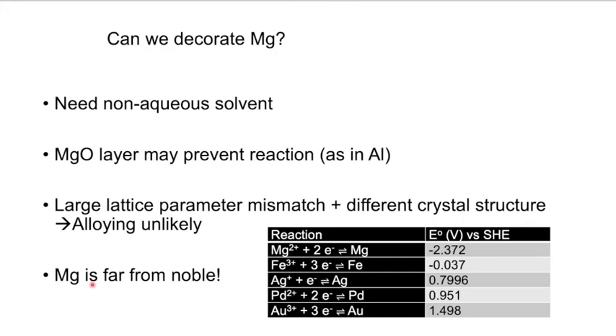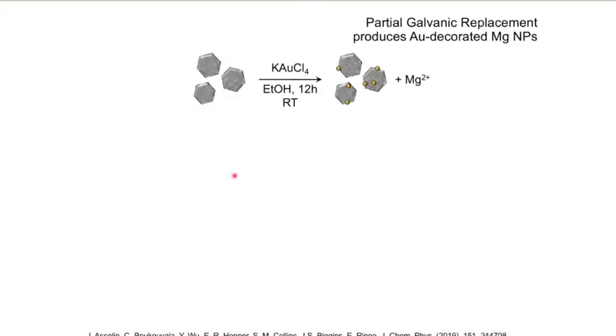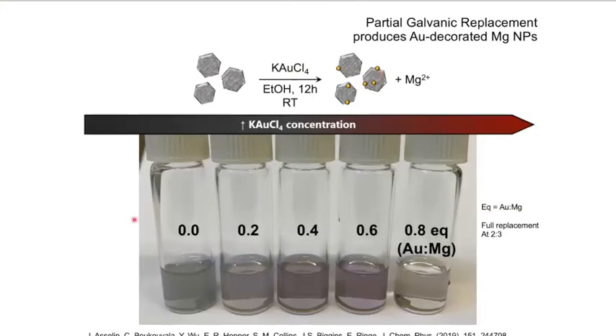And so there's a huge thermodynamic driving force to overcome this oxide layer and to drive a galvanic replacement, and it works, okay? So we're gonna be taking our particles, we're gonna do this in ethanol, room temperature, just a pinch of another metal, say a gold salt. And what we're gonna end up with is gold metal, a little bit of magnesium ion, so magnesium 2+, and if we control the stoichiometry right, there should be a little bit of magnesium metal left to do its plasmonics. And this is an example for gold.